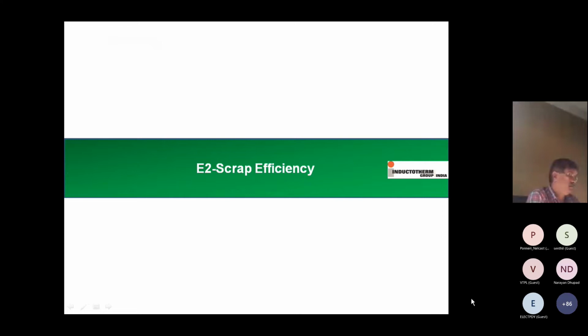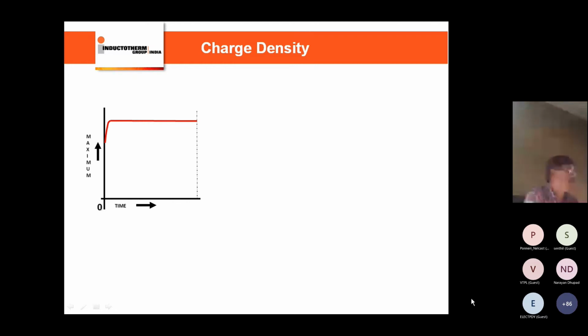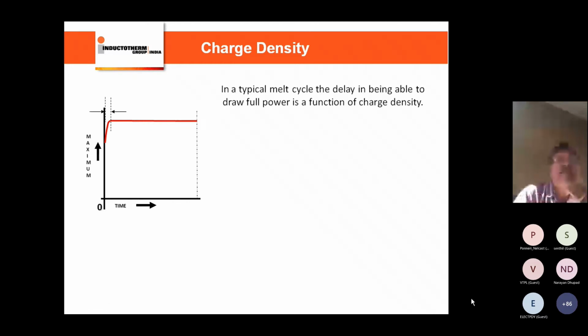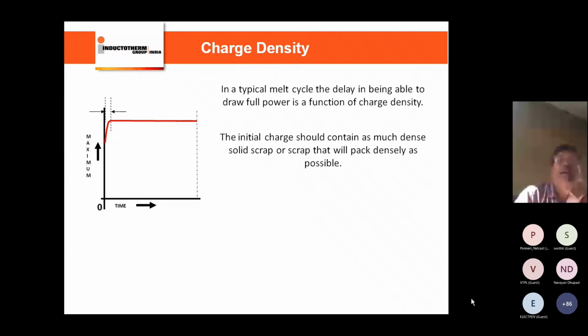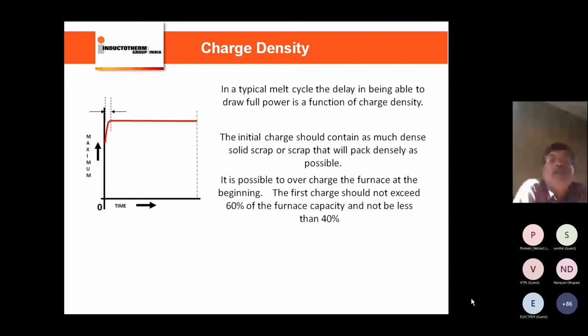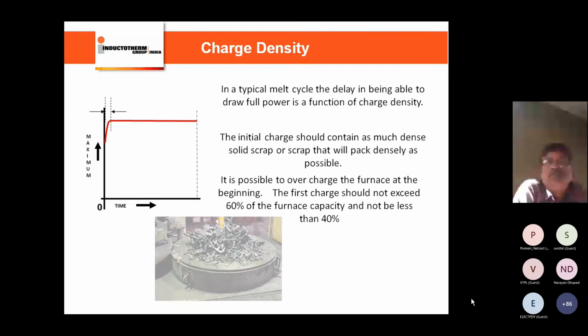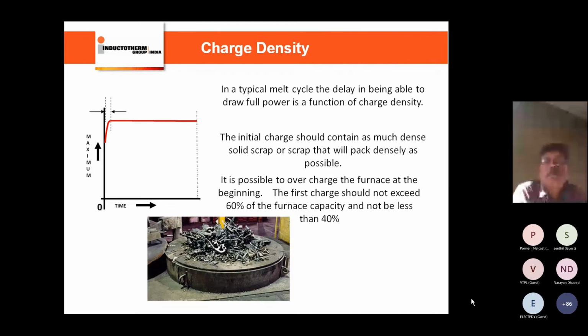Now coming to the scrap efficiency, E2. The main point is the charge density. In a typical melt cycle, the delay in being able to draw full power is a function of charge density. The initial charge should contain as much dense solid scrap, or scrap that will pack densely, as possible. It is possible to overcharge the furnace at the beginning. The first charge should not exceed 60% of furnace capacity and not be less than 40%. So the charge density is very essential in feeding the furnace to draw full power from the beginning. At the same time, one should avoid overcharging above 60% of the furnace capacity.